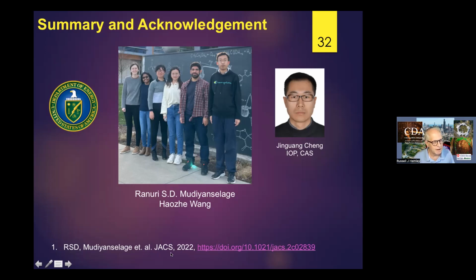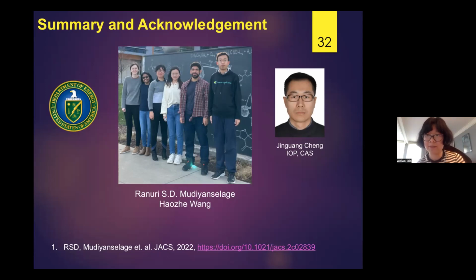Maybe I'll start with some technical questions. You mentioned the diamond cell work at very high pressure earlier, but you are also using a different kind of presses for the synthesis. You're using Walker type presses, I guess. So what was the maximum pressure you could go to in those synthesis experiments? So for synthesis experiments, we can go to 8 GPa. That's for sure. But most of the time we go to 6 GPa.